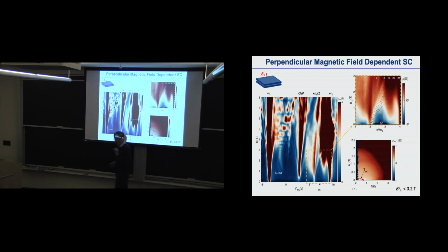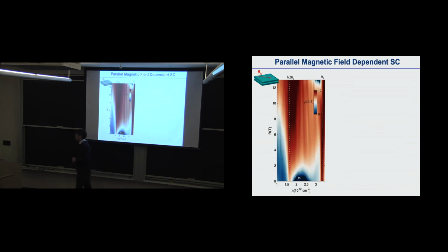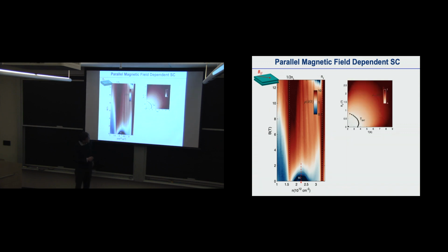So the strongest evidence is what happens if you apply an in-plane magnetic field in the system, and ask how the superconductivity changes. Like before, we apply the in-plane magnetic field to the correlated gap and dope to get superconductivity, asking how it changes. In-plane magnetic field also kills the superconductivity, but how does it get killed? If we look carefully at constant density and plot the phase diagram versus B versus T, you start to see that the phase diagram is very different.